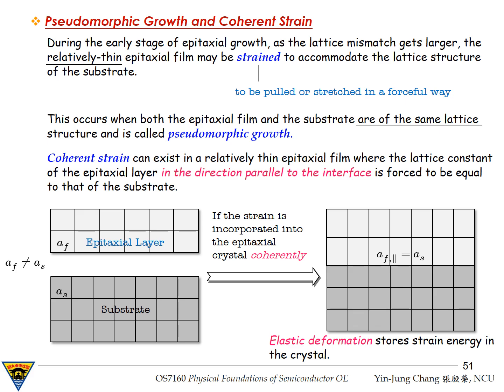However, there is an important limitation. Elastic deformation stores strain energy in the crystal. As the thickness of the film increases, the total elastic strain energy also increases. Eventually, the system reaches a point where maintaining coherent strain becomes energetically not possible. So when that happens, the system relieves the strain by forming misfit dislocations, which we will discuss shortly. But for relatively thin films, pseudomorphic growth can be maintained, and this strained state is actually very useful in semiconductor device engineering.